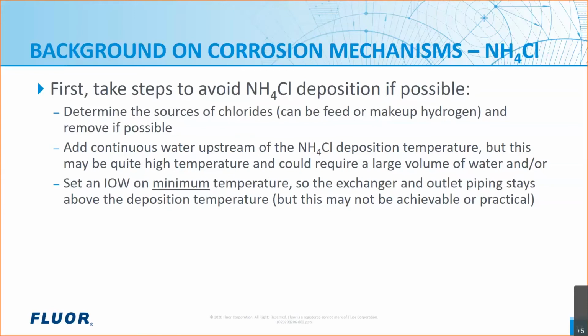The second step that's looked at is, can we add a continuous water wash upstream of the ammonium chloride deposition temperature? But this is often tricky too, because that could be a very high temperature, because say the deposition would occur in that last shell and tube exchanger on the process flow diagram. Now you have to put the water wash upstream of that, and that's going to be quite a high temperature. It would require a huge volume of water, and might be difficult to get a good distribution. So that's often very complicated.